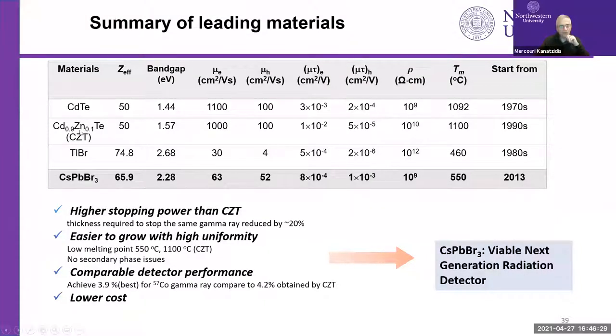When you put a little bit of zinc in the structure, the band gap goes up from 1.4 to 1.6. Now this is high enough to get higher resistivity. The mobilities are not affected significantly. And this is the material actually that made it to commercialization for gamma rays. Cadmium telluride is used for X-rays in a limited fashion.